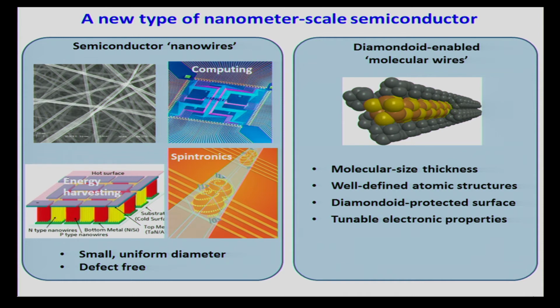We have a molecular size thickness of this wire. Remember, in this copper sulfide with adamantane, we have essentially only 3 atoms in the cross-section of the copper sulfide core. We have a very well-defined atomic structure, and we have the diamondoids surrounding them as a surface protection, so you don't have surface defects such as dangling bonds and add atoms.